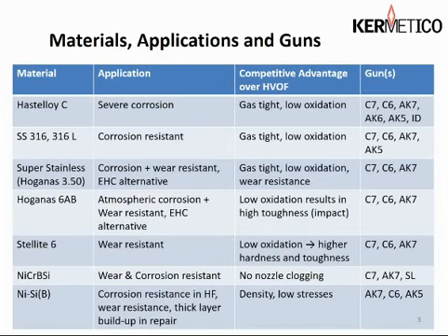And the nickel silicon coating, it's got a little boron in it, but not as a self-fluxing alloy. It's corrosion resistant to hydrogen fluoride, which comes out of the chemical companies. We'll be talking about that a little bit later. It's a very dense and low stress coating. We can make it very thick, and we've used that in all our major OD guns.